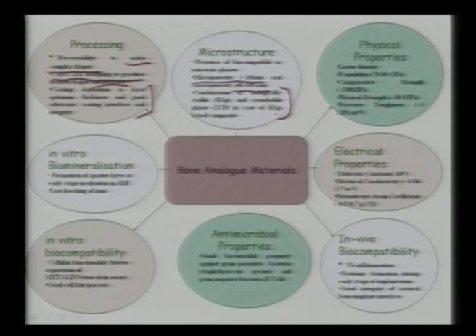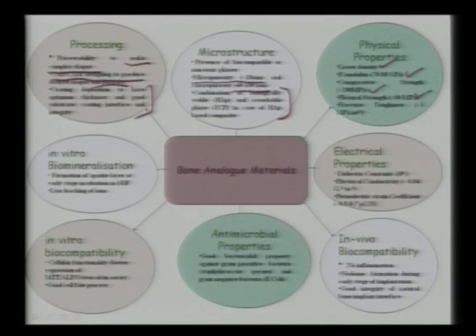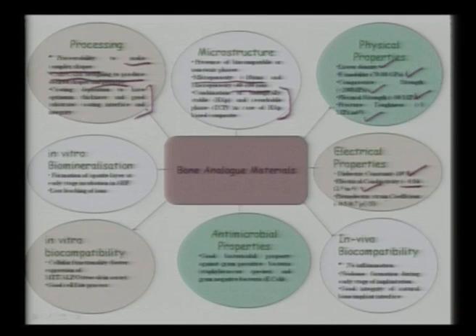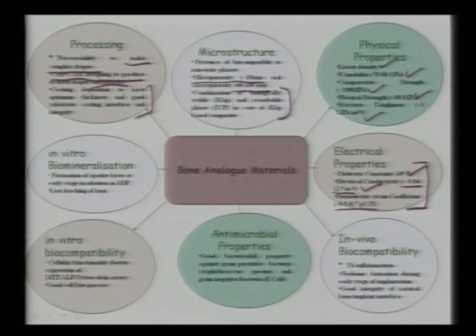Electrical properties are also important because bone itself is a piezoelectric composite of organic and inorganic phases. The bone analog material should have a dielectric constant around 1000 or more, electrical conductivity of about 0.04 ohm⁻¹m⁻¹, and a piezoelectric coefficient of 0.5 to 0.7. If all these property combinations are ensured in the synthetic biomaterial, it would be an ideal bone material.